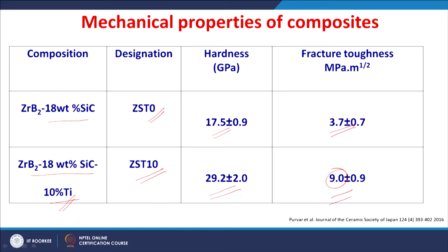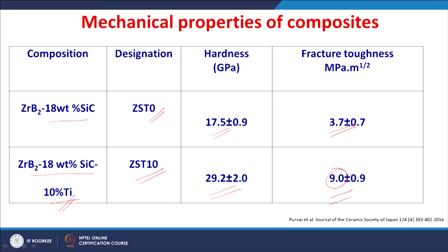It also indicates the densification is improved by adding titanium, that reflects in the microstructural characteristics and then the mechanical properties. In another study it was also found that the grain size of the zirconium diboride and particle size of silicon carbide are almost similar to what we started with as the initial powder particles. There is not much difference in the average particle size of silicon carbide or average grain size of the zirconium diboride. This also indicates the spark plasma sintering conditions were sufficient to prepare a material of high density with good mechanical properties. Among the two investigated composites, the composite with the titanium addition showed higher hardness and higher fracture toughness.